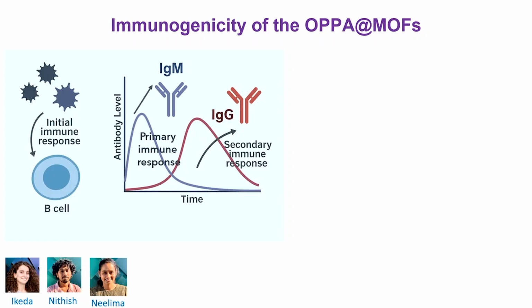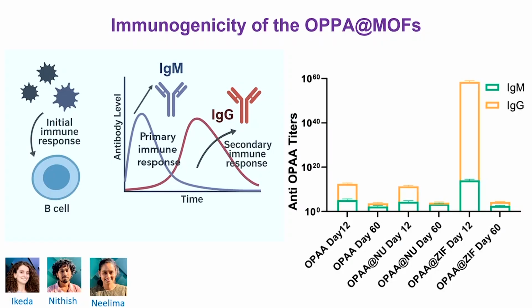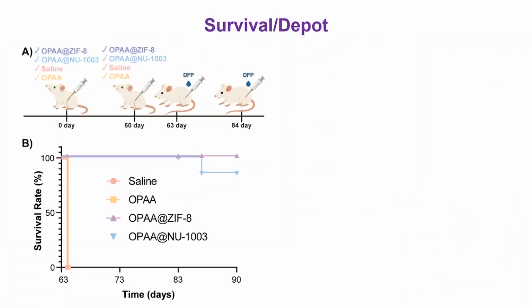And the second thing is, I've been taught by my biologist friends that you want to see that your body is not reacting against what you are injecting. And what you see here with our material is that you could go to almost 60 days with multiple injections and you see that your body is behaving the way it's supposed to behave. Versus the ZIF-8, which after a few days starts to behave a little weirdly.